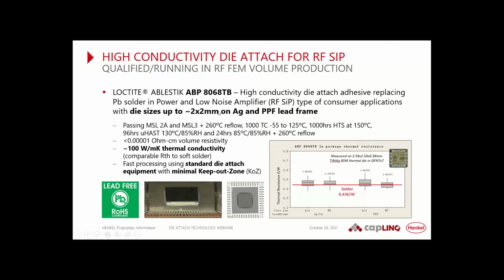It got qualified in power low noise amplifiers, die sizes up to 2x2, on a silver and a PPF lead frame, and basically having about 100 watt per meter Kelvin thermal conductivity. And as you can see, a very controlled fillet. One of the key things here as well is this works like a standard die attach, like a standard SR4, like the QMI2529 LV Chris talked about. So there is no difference, no press. It sinters at 200 degrees, a little bit higher than maybe a die attach paste, but it's comparable. And in the end, it has a thermal conductivity measured in package comparable to soft solder.